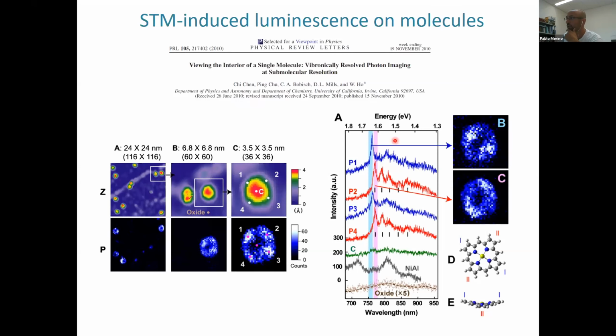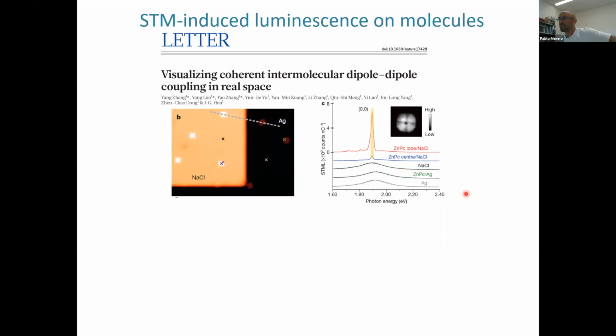And what they saw is that, depending on where you inject into the molecule, you can get two different emissions. The blue one here when you inject on these two lobes, and the red one when you inject on the other opposite red lobes. And this really boosts the field, and people started to look for other systems, and rapidly, in 2015, the group of Zhen-Chao Dong in China discovered this system, which has become a prototypical system of STM, photon STM or STM-induced luminescence studies, which is phthalocyanines, and zinc phthalocyanine in particular, on top of salt layers on silver in this case.